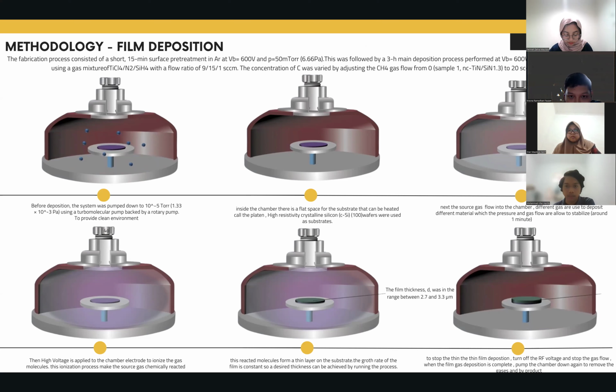This process also has a pressure of 6.66 Pascal, and there is a 3 hour main deposition process. To stop the thin film deposition, we turn off the RF voltage and stop the gas flow. And when the film deposition is complete, we pump the chamber down again to remove the gases and the byproduct.